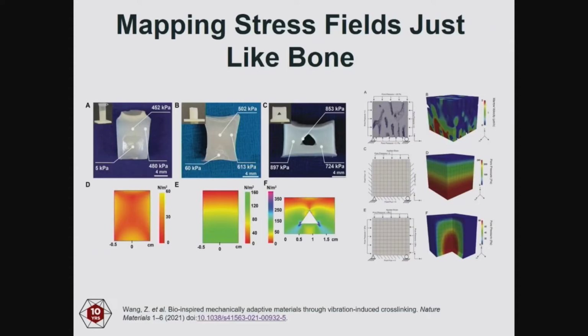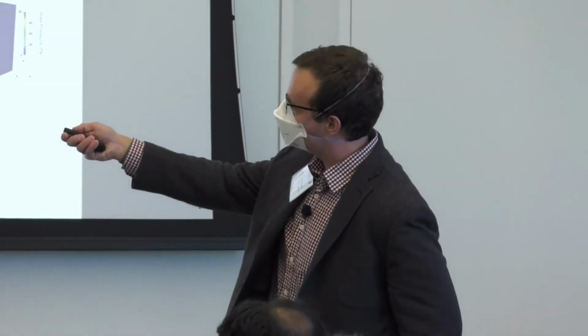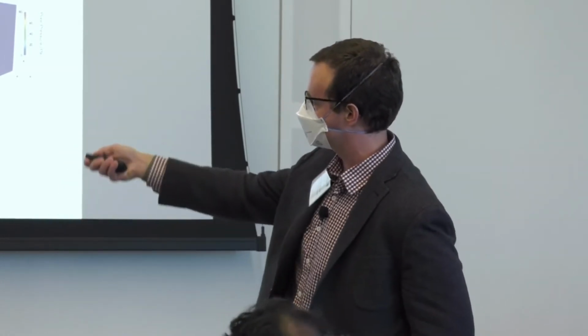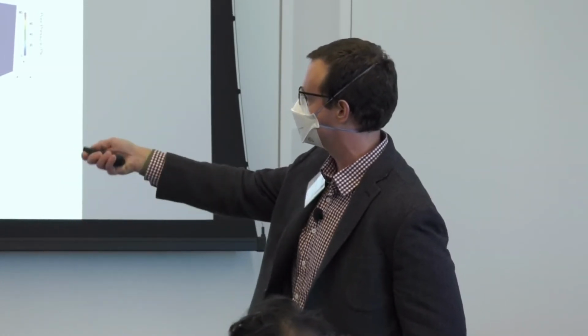And the last thing that I'll leave you with, that we didn't expect to occur, but were really pleasantly surprised by, is that when we cut these larger samples open and examined them, there were hard and soft materials inside of the larger sample. And it turned out, when we modeled the stress fields, the actual stress field that the material is feeling, the von Mises stresses as they're called, that the material was actually mapping the stress that it was experiencing. So when we did it inside of a flask, it experienced a different stress field. When we left it outside the flask, it experienced a different stress field.